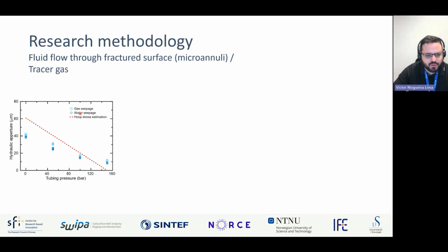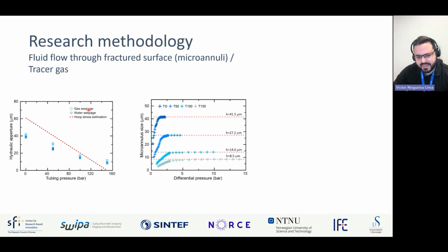We applied both gas and water seepage tests. This point is also connected to what Nils said in his presentation. When we performed the gas test just after the curing process, the cell was almost in dry conditions, so it could have a very close behavior between the gas seepage and the water seepage. Then when we go to the two-phase flow test, we saturate the cell with water and do the gas seepage.